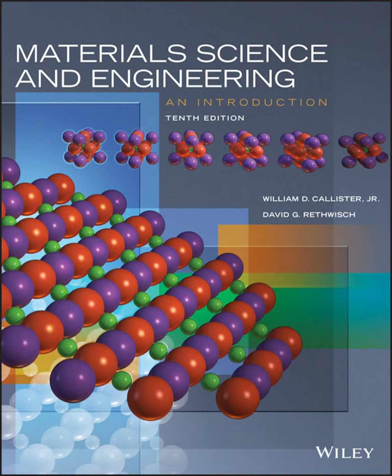Exactly. And to visualize steady state, think of that thin metal plate again. Yeah. High pressure gas on one side, low pressure on the other. Gas diffuses through. If you could plot the gas concentration inside the plate versus position, you'd get a straight line, a linear profile. The slope of that line is the concentration gradient, dC/dx, or delta C over delta X for a straight line. A real-world example, purifying hydrogen. You can diffuse it through a palladium sheet. Palladium lets hydrogen through, but blocks other gases. That's steady-state diffusion at work.